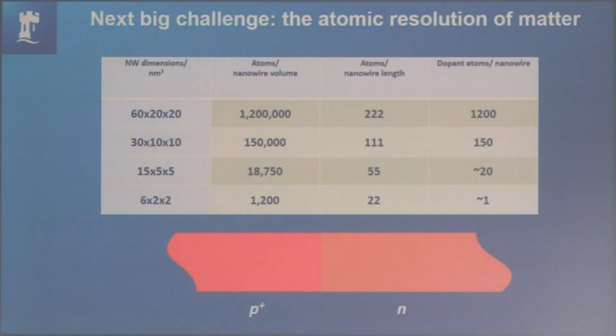But as we did that, we did it by making everything smaller and smaller. So if I looked at, say, a silicon nanowire and it was 60 nanometers by 20 nanometers by 20 nanometers, I'd have roughly 1 million atoms. And if I took a reasonable level of doping, I would have about 1,200 dopant atoms in that volume.